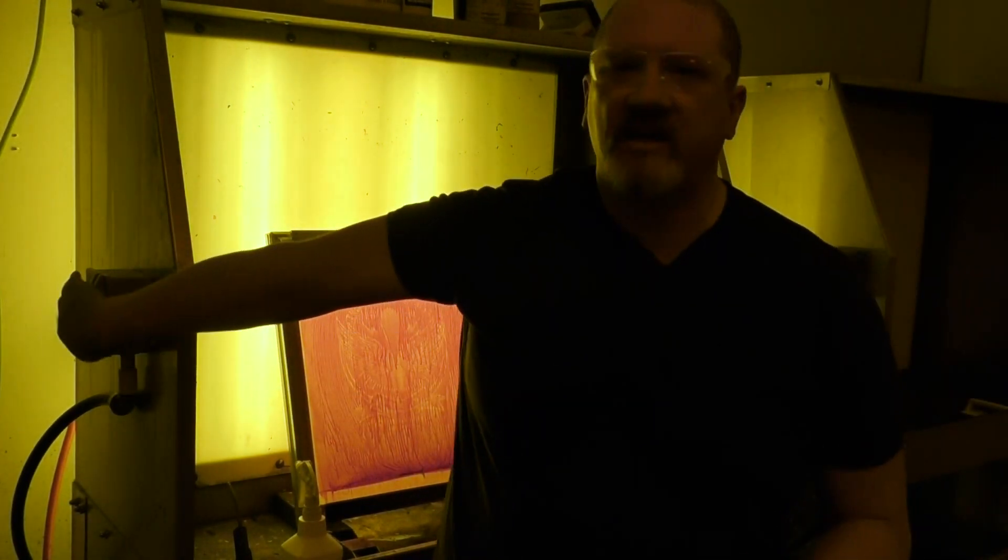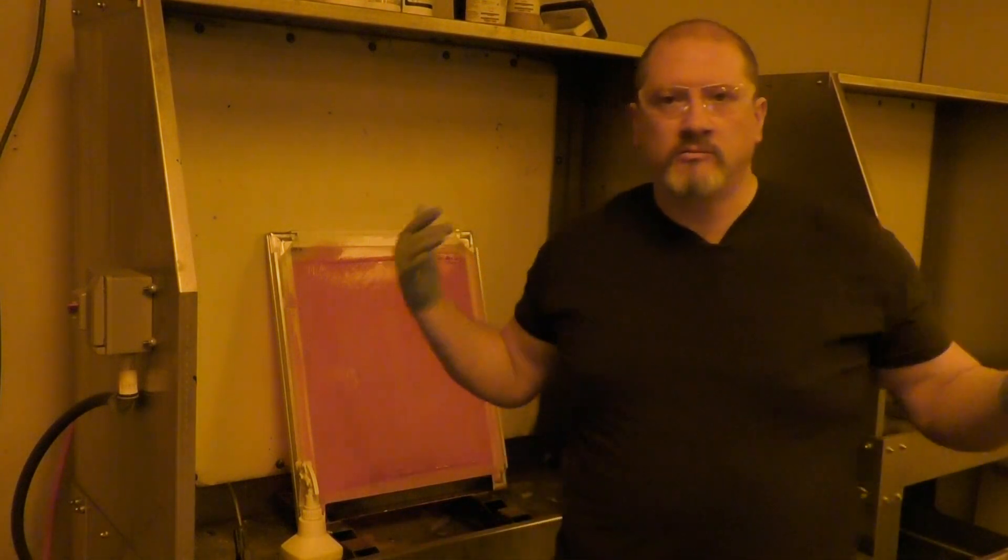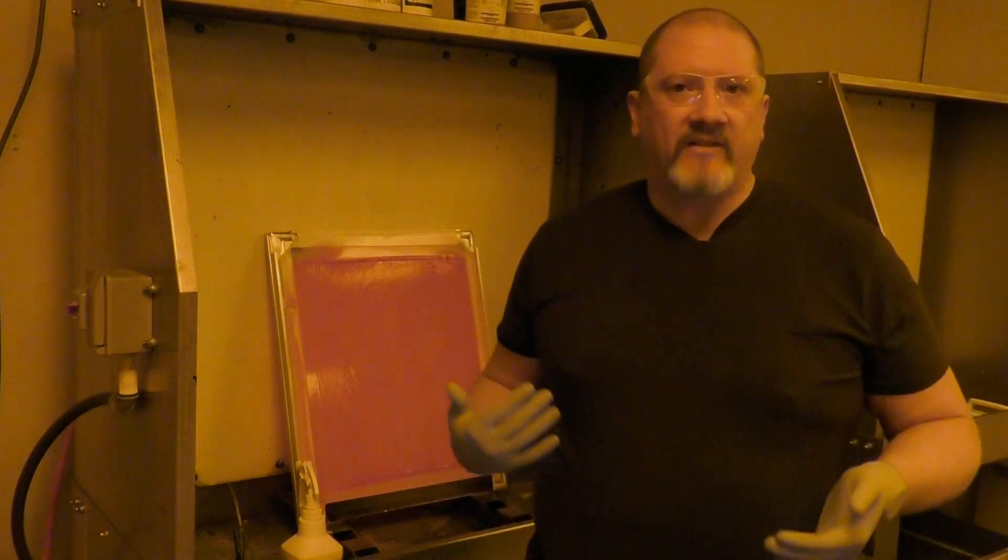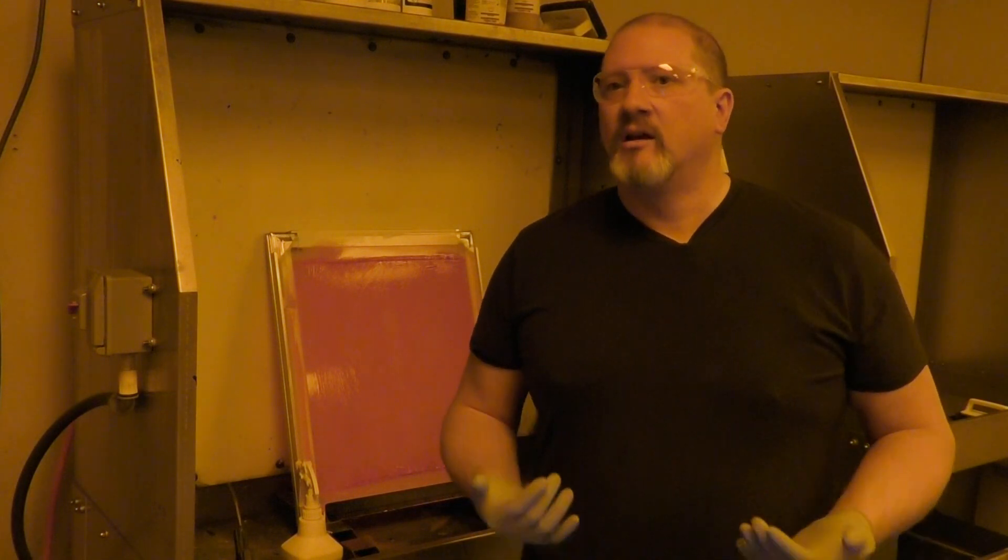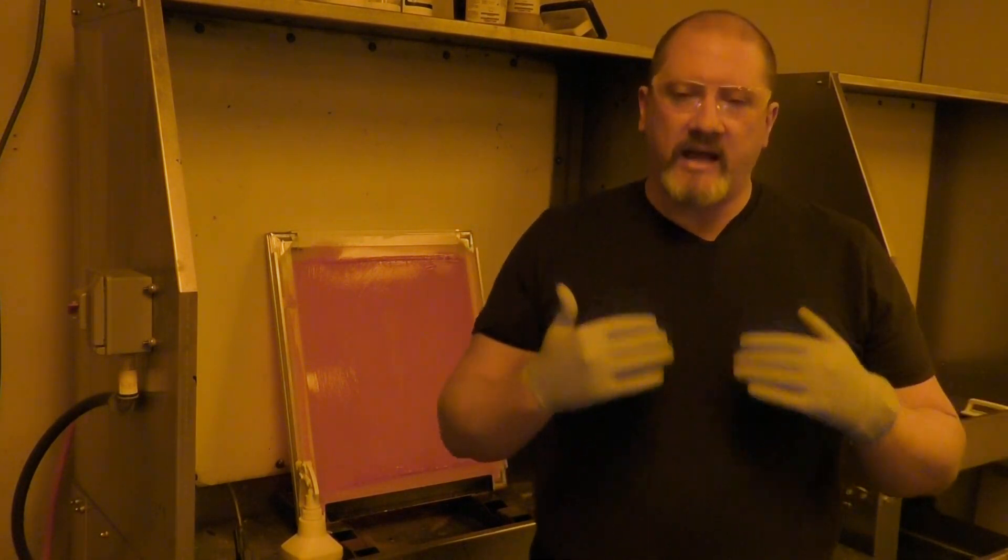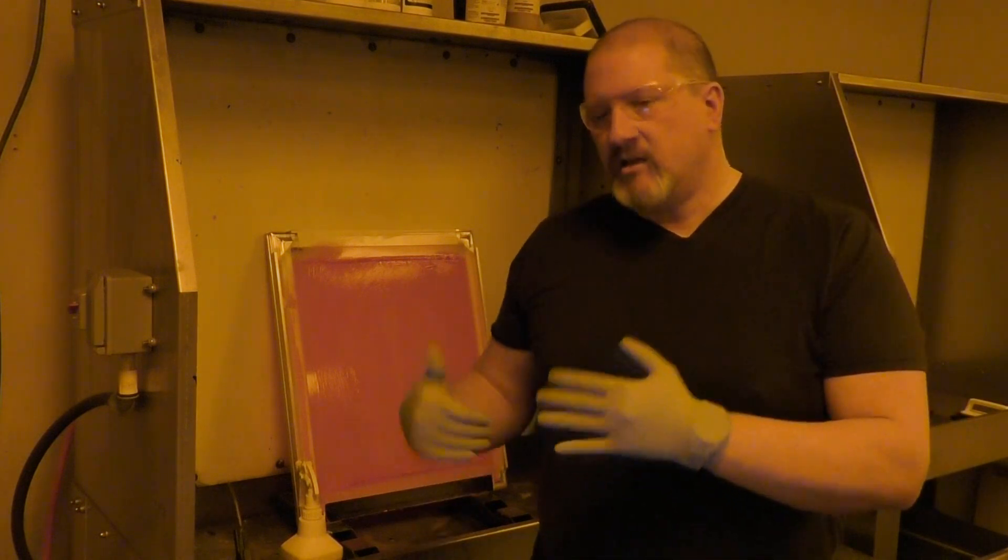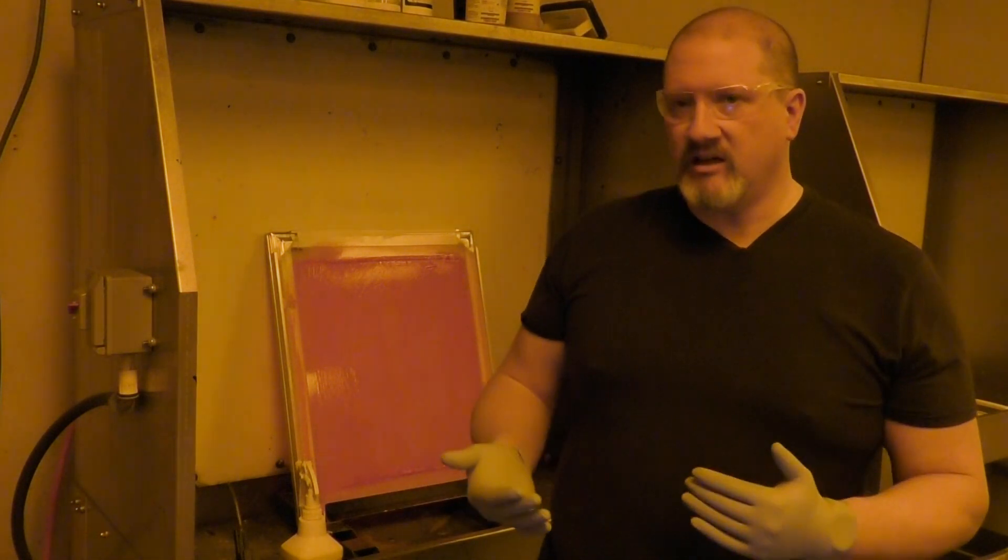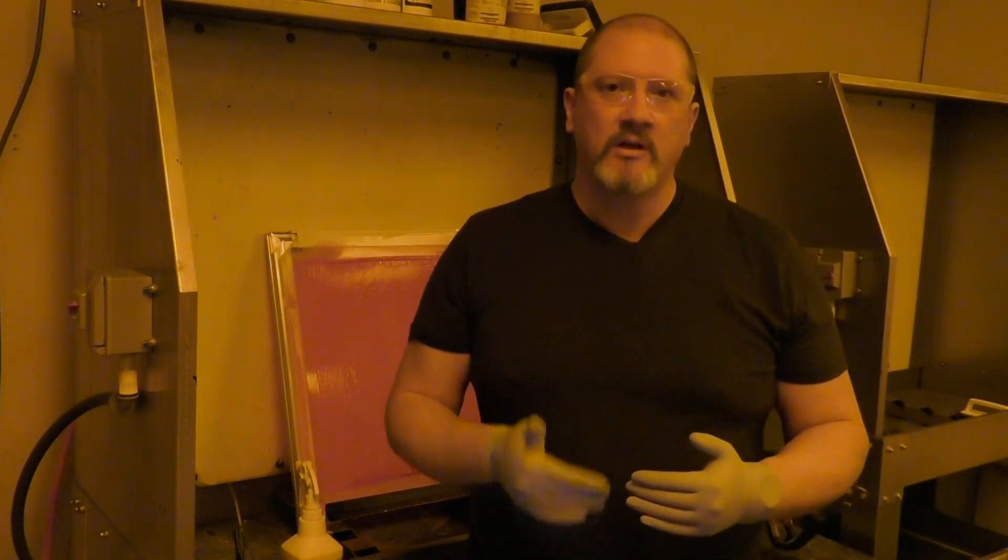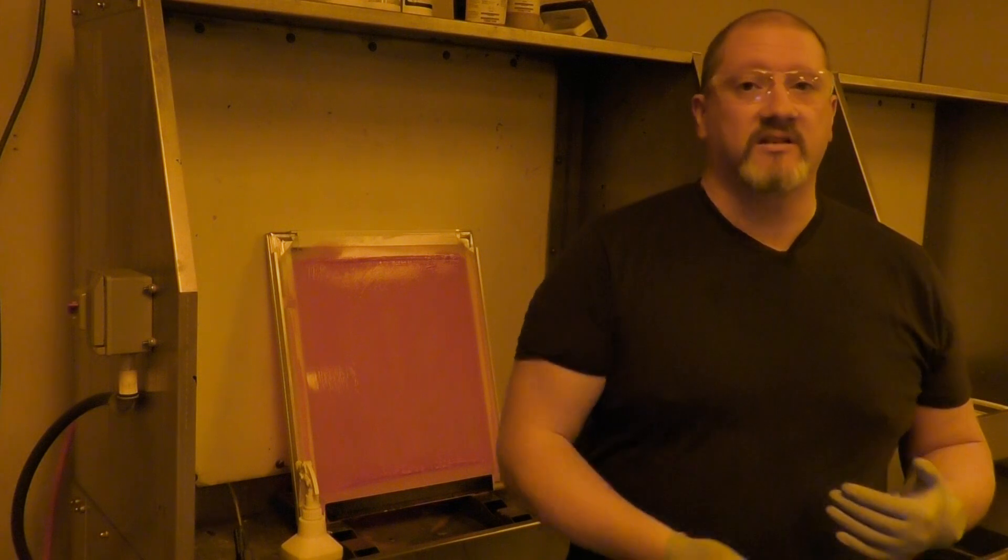One of the other things I wanted to talk about is the lifespan of stencil remover, of emulsion stripper. It's something that we've all run into at some point or another, where if we're using a dip tank or we're spraying on, we have some stuff sitting around and it's just not working as well anymore. There's a couple of reasons for that. All stencil remover main chemicals, the periodic acid, has a shelf life. It's approximately a year from the date on the label of the product that you bought. It basically starts to break down over time and it loses its efficiency and its efficacy.